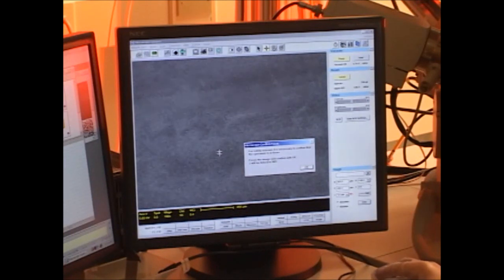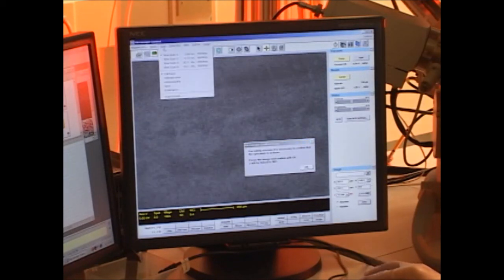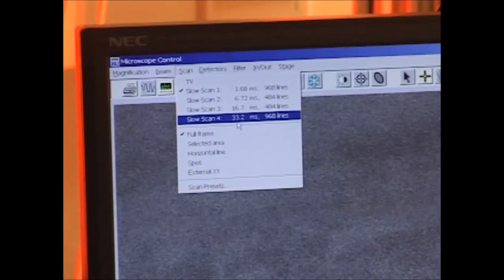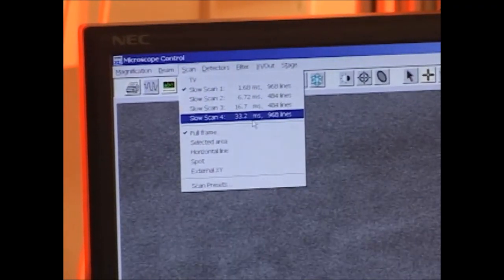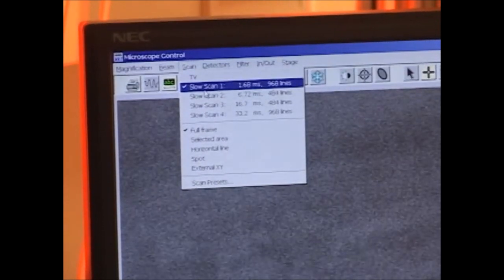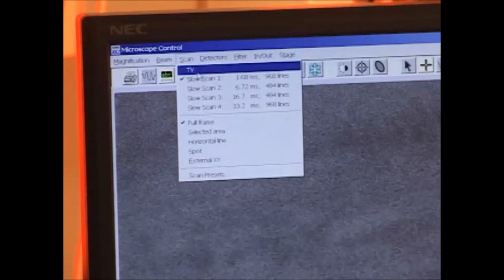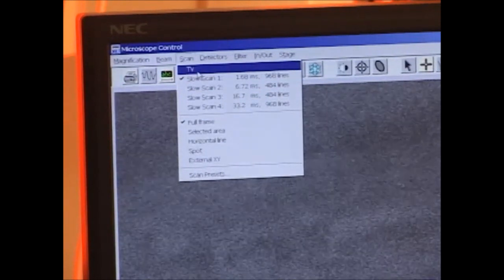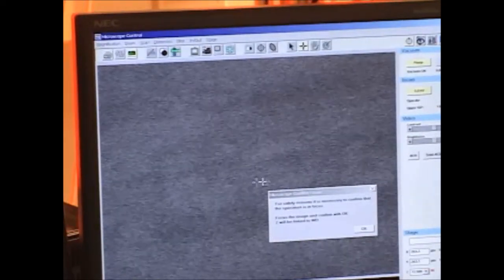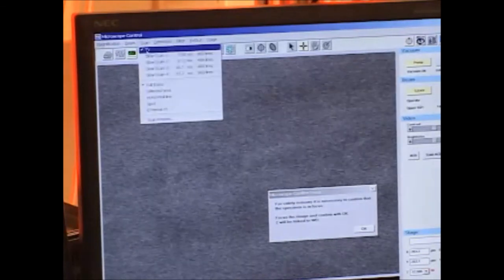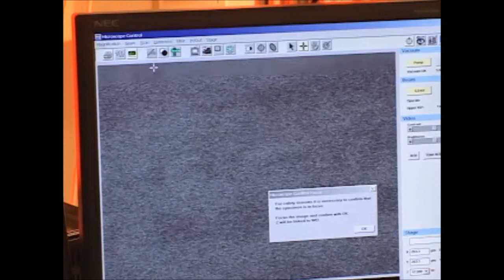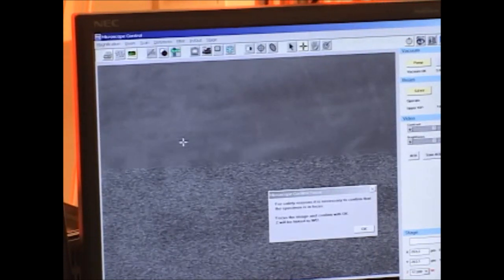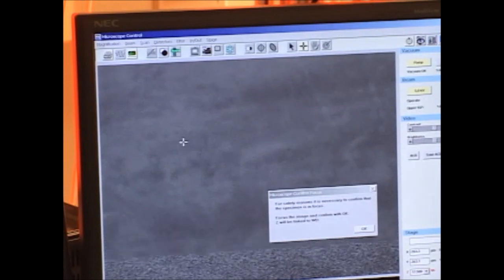You can see the beam raster scanning across the surface of the sample. The scan rate can be changed under the scan tab here on the upper left. In the top menu, you see I have 5 different choices, ranging from TV, which is the fastest scan rate, down to slow scan 4, which is the slowest scan rate at 33.2 milliseconds. If you watch the change in the screen as I go from slow scan 1 to TV, you'll notice that the resolution gets a lot worse. TV mode is good because it updates the screen quickly, but it has a very low signal to noise ratio, and so we see a lot more static in this image. Slower scan rates have a lower refresh rate, but they have a lot less noise in the picture.